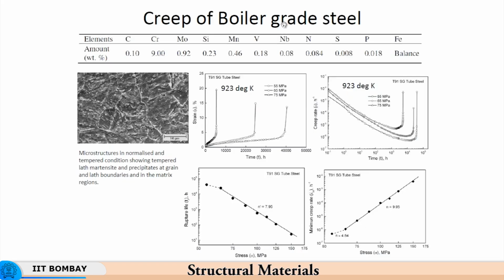properties, we have creep properties of boiler grade steel. You see that the chemical composition is this. So, this is called as a T91 tube steel, or basically boiler grade steel. So, chromium is 9%, molybdenum is 0.92, and some amount of manganese, and the other elements are meant for grain size control, or basically carbide formation, and for precipitation of carbides in general.